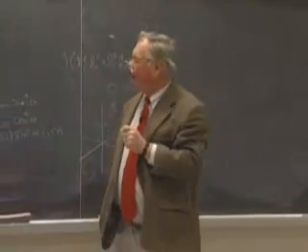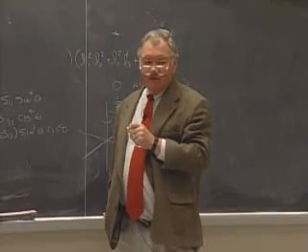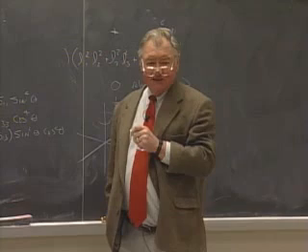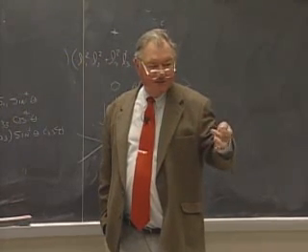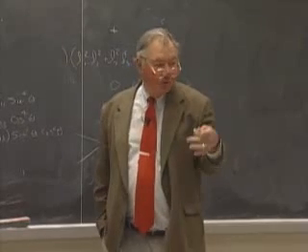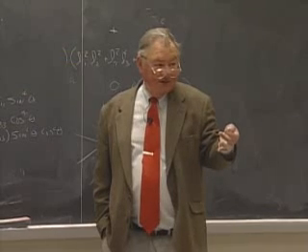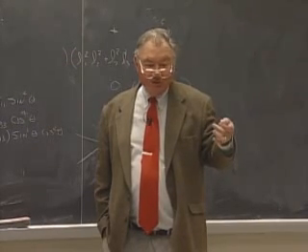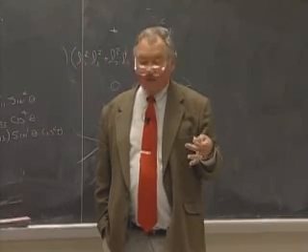And there are many, many materials in here. Simmons and Wang, interestingly, are geophysicists. Why should geophysicists care about stiffnesses? Because these guys are going all over the face of the Earth, setting off little bits of explosive that send off seismic waves, and they probe the interior of the Earth by the propagation of elastic waves. And the elastic waves depend on the square root of stiffnesses over the density of the material.